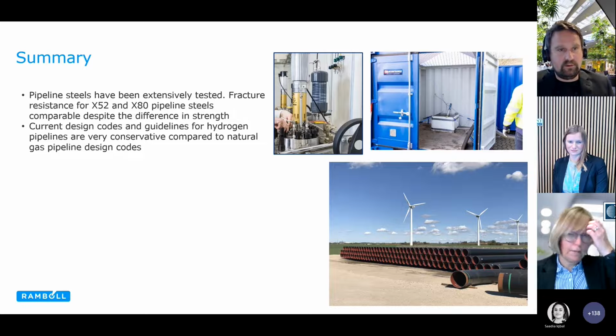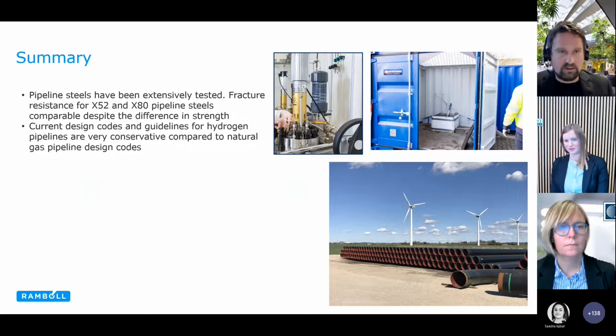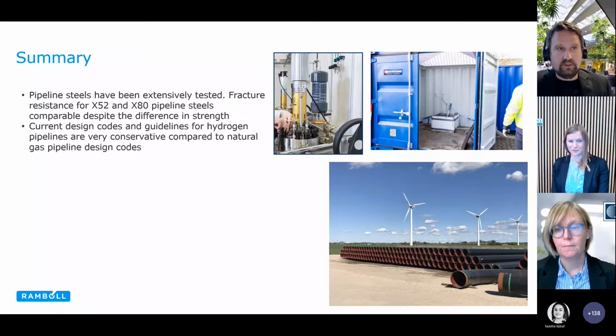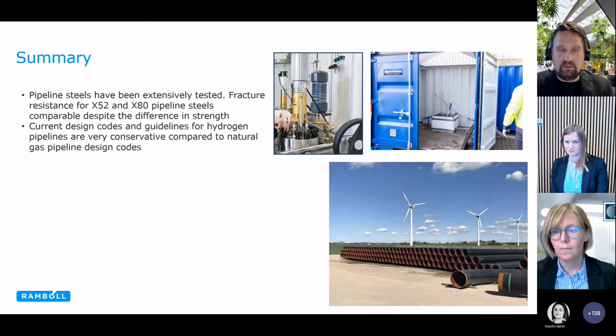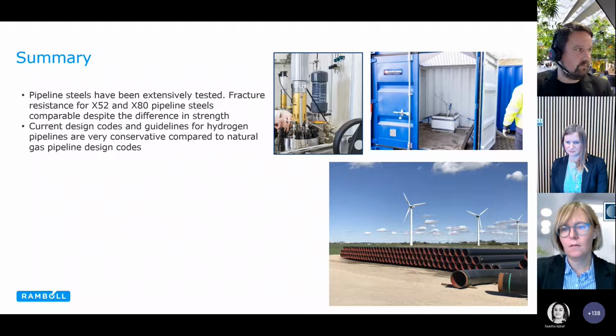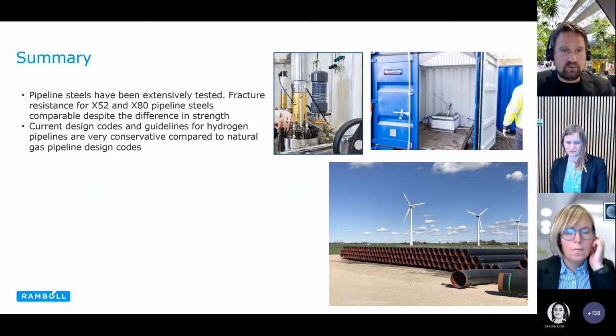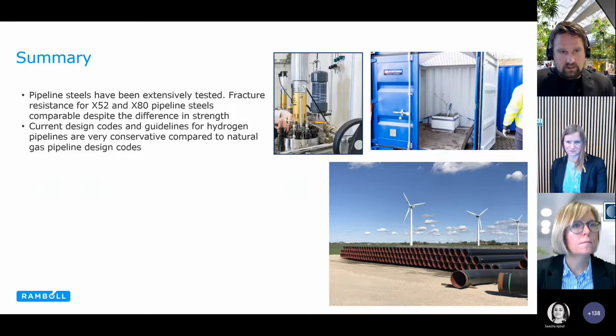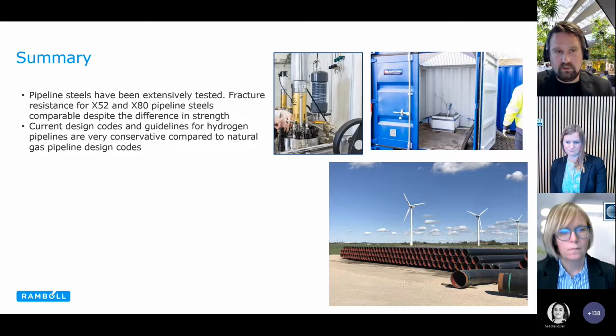There is a lot of conservatism in the design codes and guidelines compared to the natural gas pipeline design codes. And this is probably something very reasonable to do, but it seems that the signs of relaxation would be, maybe with some conditions or with some additional testing applied, that there's coming more room to relax some of these, or at least, for a pipeline designer such as myself, some sort of a practical way to not design with too much steel or with too low yield strength or for too low pressure.